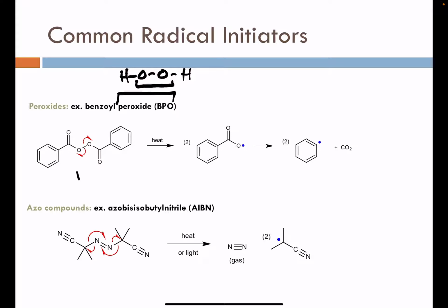Okay, so here we recognize that peroxide in the middle. We can see that oxygen-oxygen single bond is very reactive and prone to degradation under heating. So by heating this, we get what's called homolytic cleavage. So the same, homo to both sides, lytic, the break. So we're going to break that oxygen-oxygen single bond evenly to split the molecule into two fragments. The first product here is listed here, and here we have two radicals where we have an oxygen-centered radical.